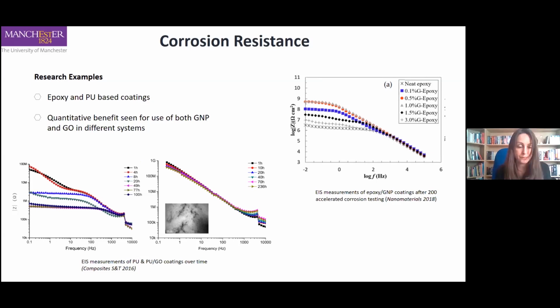This graph's really useful. I think it gives so much more information than pass or fail. Does graphene work well? Does it not? It gives information on dose and critical limits. If you look at the low dose levels, the 0.1%, the blue line here of graphene, the result's not as good. And that's probably because the addition level is actually too low to form that barrier network in the coating. And likewise, although slightly better than the neat epoxy, the 1.5% and the 3% gave lower performance as well, and they lose efficacy. And this is probably due to dispersion and agglomeration issues, which I'm going to discuss in a lot more detail later on. So for that reason, it's a good graph.